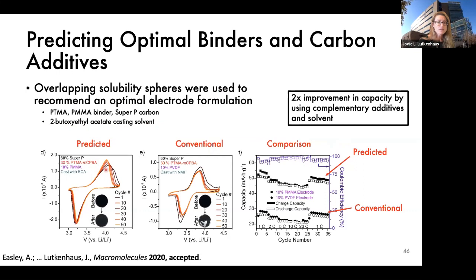And what we saw was that if we used the predicted composition, we have really good electrode stability. In fact, the CV is even growing in as electrolyte begins to penetrate it. So it's not dissolving, it's actually compatibilizing with the electrode. And if we use the conventional electrode formulation, the electrode eventually delaminates and we have a loss of activity, which was the original problem. So you can see that here where our predicted composition has a capacity that's generally 2 times higher than the conventional composition. That's with the same electrolyte. We just optimized the casting procedure.